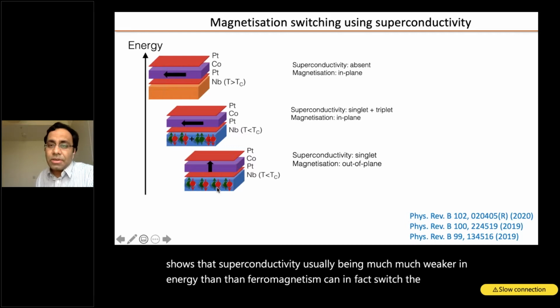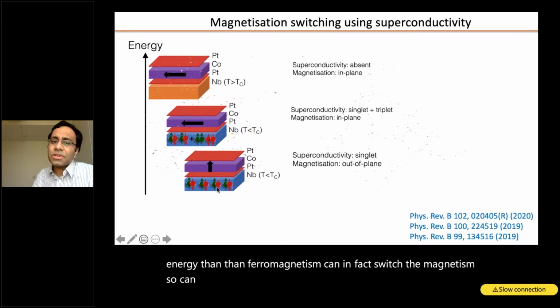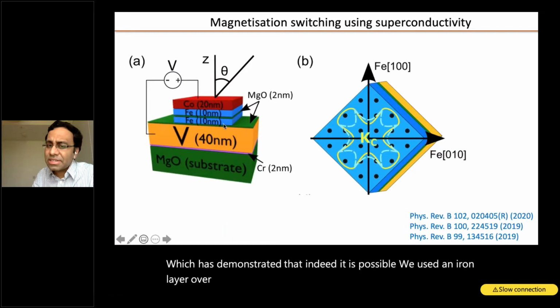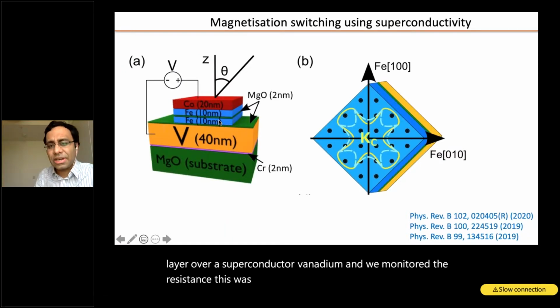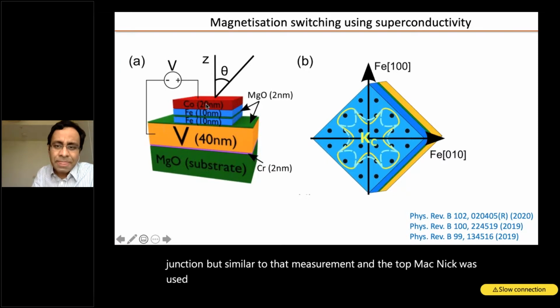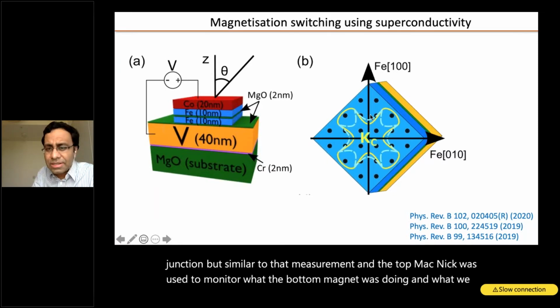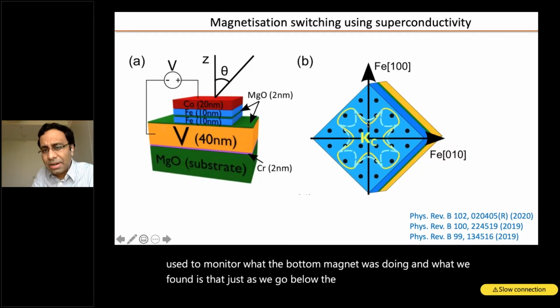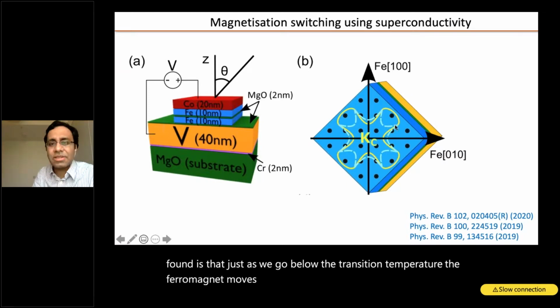This was recently demonstrated. We collaborated with a group in Spain, which has demonstrated that indeed it is possible. We used an iron layer over a superconductor, vanadium, and we monitored the resistance. This was not exactly a Josephson junction, but similar to that measurement. And the top magnet was used to monitor what the bottom magnet was doing. And what we found is that just as we go below the transition temperature, the ferromagnet, rather than staying at the minima in energy here, develops an additional minima at 45 degrees. So the ferromagnet automatically switches at 45. And recently, in collaboration with that group, we found out that it is possible to switch the magnet in the out of plane direction as well.